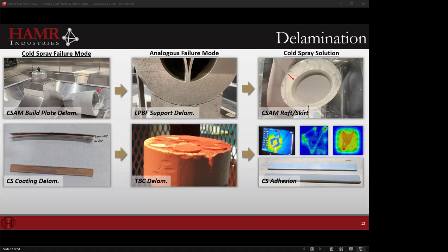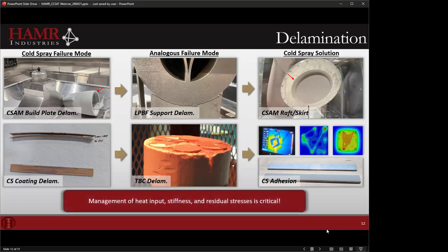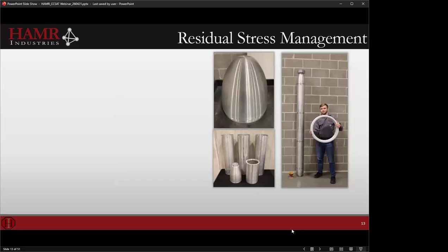And then from the coating side, a lot of it comes down to thermal input and managing thermal expansion and mismatch stresses. And you can see from the left to the right that we're able to get these coatings to adhere. So fundamentally, much of this comes down to management of heat input, stiffness, and residual stress, similar to what we do elsewhere. It's a similar challenge that we have to face in cold spray. And it's a good segue to overall residual stress management.